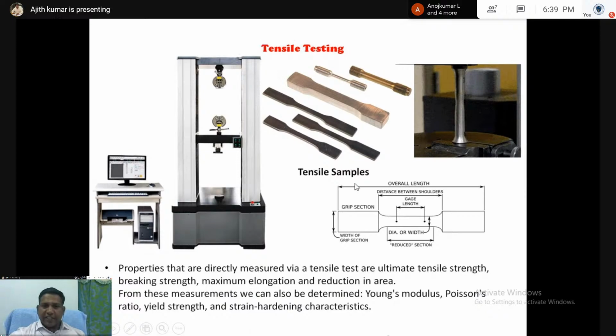These are the tensile testing samples. We make tensile testing samples also in our laboratory. From these tensile values, we can get the Young's modulus, Poisson ratio, yield strength, and strain hardening capacity. Creep is a plastic deformation of the metal that occurs as a function of time at a constant load or stress. So creep is a time-dependent process where a material under an applied stress exhibits a dimensional change at high temperature. The process is also temperature dependent. Creep always increases with the temperature.